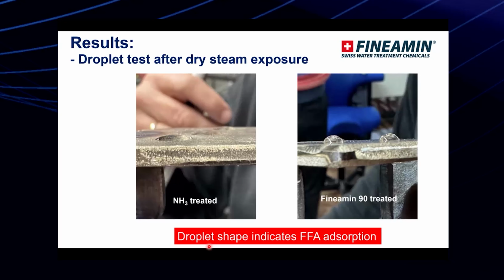In the droplet test, we see a difference, a clear indication of FFA adsorption. As you can see, the difference on the metal plate. This is after we take the test specimen and cool it down, and then we do a droplet test, and we could see a clear difference in terms of the hydrophobicity of the metal plates, compared with those with ammonia. And we could see with the Fineamin 90 there is much better hydrophobicity. And bear in mind, this is only 8 hours of absorption from the dry steam.